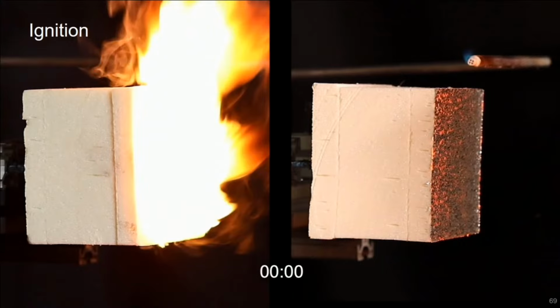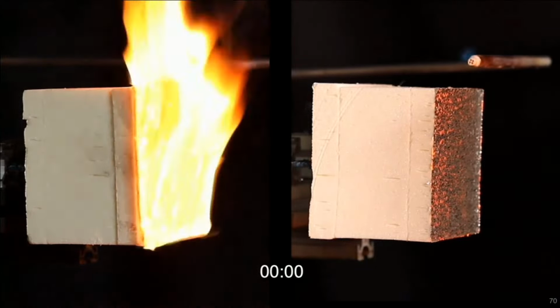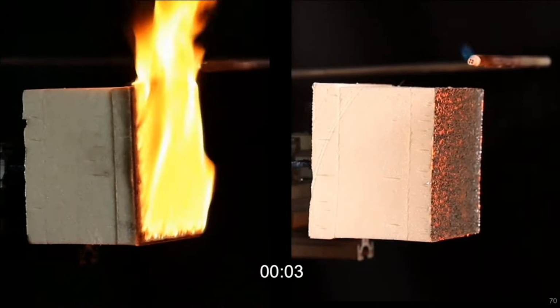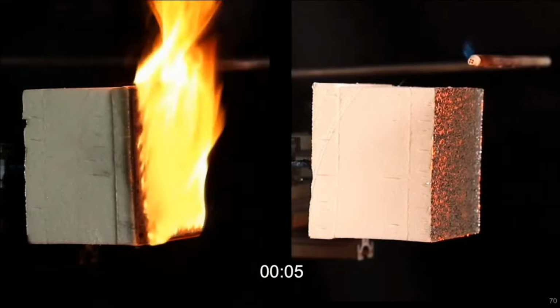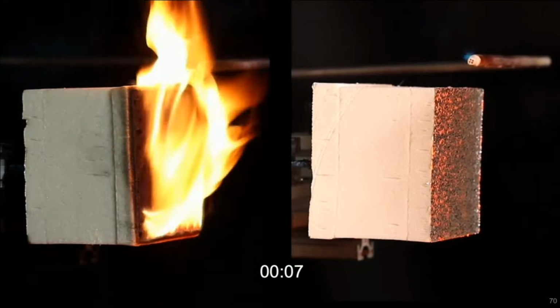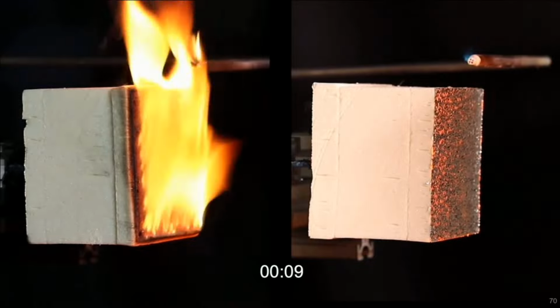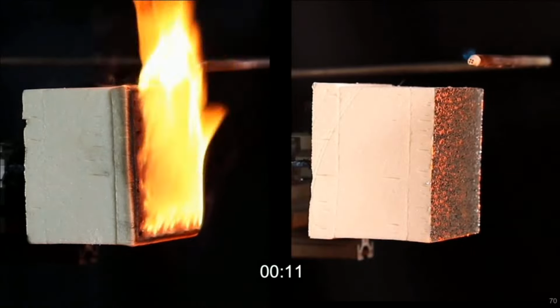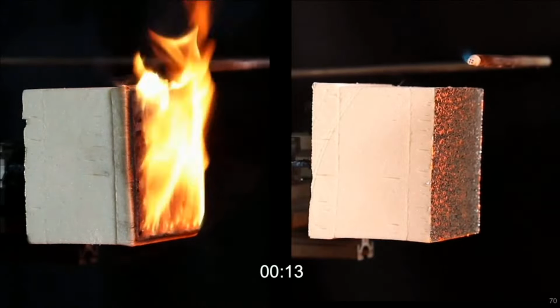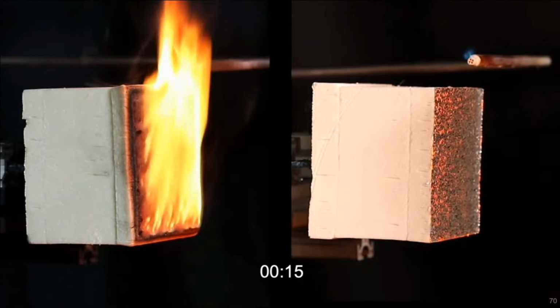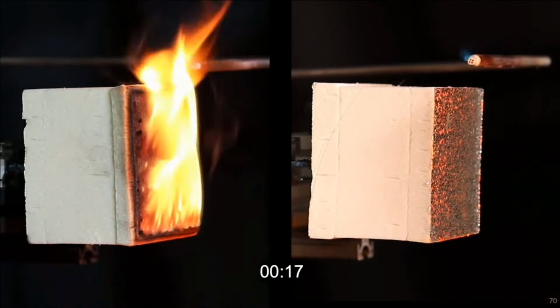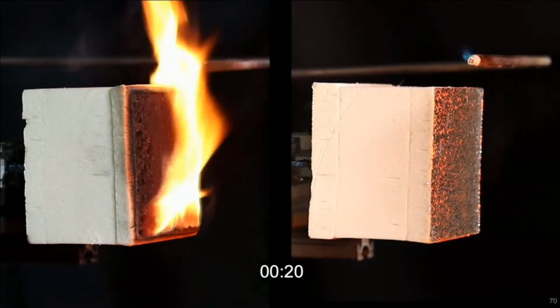So you can see ignition at time 0 in this case, which is the moment that the radiant panels actually come to a rest in front of the sample. So they ignite essentially instantaneously. After ignition, there's no obvious melting or dripping, again, because these are thermosetting polymers. We see continuous flaming and the formation of a char layer over the surface of the left-hand sample. This results in a gradual reduction of the severity of burning as we watch it play forward.